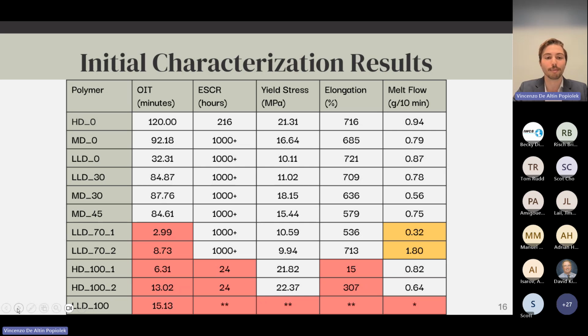Looking at our other 4 remaining blends, for OIT, which has an industry standard of 20 minutes, we see that all of the different blends failed. However, this was not of great concern to us, as OIT is the easiest property to improve through the use of antioxidants. And as such, we didn't feel the need to design around it too much, but it was good to know that we needed to add antioxidants.